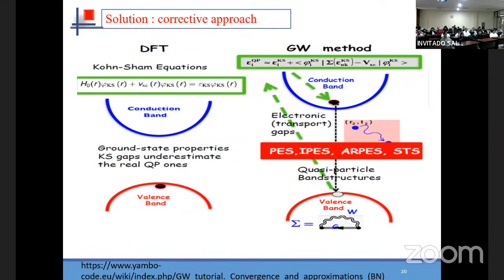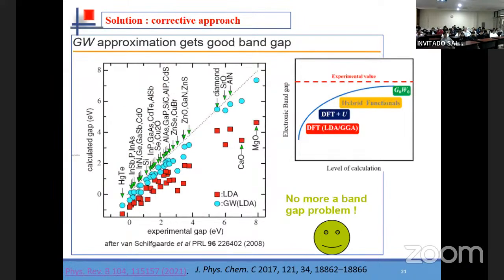And this problem is solved in the GW equation, where we take into consideration the quasi-particle energy and the excitation of particles between the valence band and the conduction band. So using the GW approach, we have no more problem in the band gap. As you can see here, the computed band gaps are close or equal to the experimental band gap.